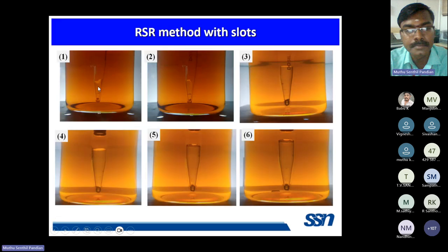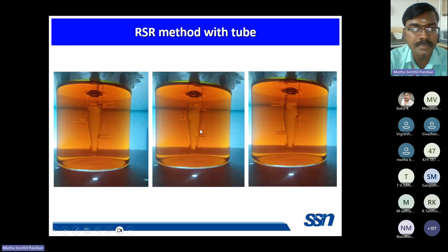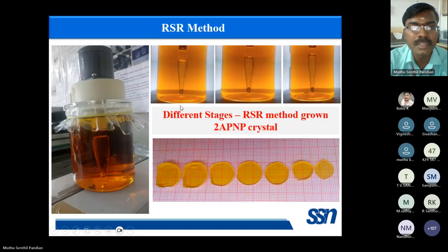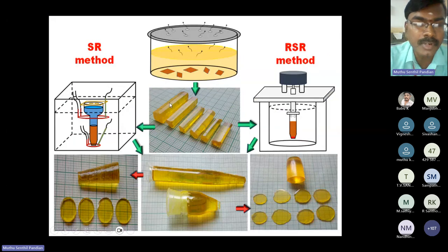So these are the different growth stages of this RSR method with the slots, and this is the RSR method with the tube. So this is an as-grown crystal. This is a cut and polished wafer. So this is the 4-nitrophenol derivative single crystal for nonlinear optical application. We have grown it in a beaker. This method is called the SEST, slow evaporation solution technique method. From this method, we have grown this crystal. And this is the same crystal grown by the SR method, and the same crystal grown by this RSR method. These are the cut and polished wafers.